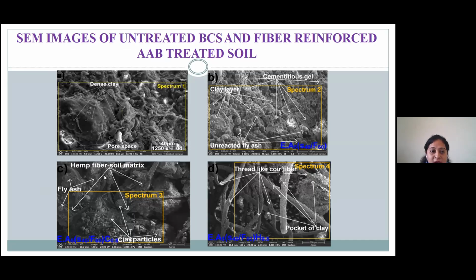This is the fly ash, and you can see the dense clay, and then the cementitious gel can be observed. We have also observed the thread-like coir fiber with pockets of clay. These are the different microstructural analyses we carried out, and the details can be found in one of our journal papers in the International Journal of Geotechnical Engineering.